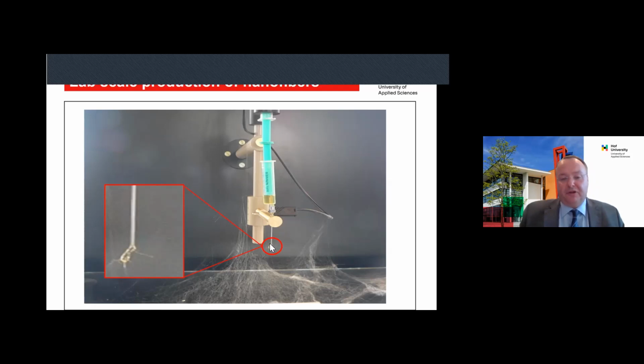we have a certain movement, and next to this we inject charges, charge carriers by the applied voltage. That means we have a really, really high charge carrier concentration in the drop. And now we have the following effect, that the system tries to dilute the charge carrier concentration. And how can we do this? We can do this if we form a jet, which tends to this side or to this side.